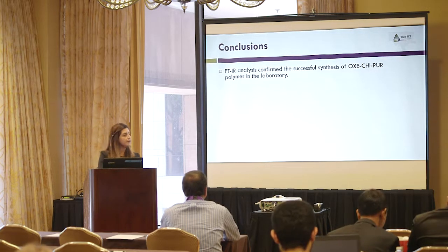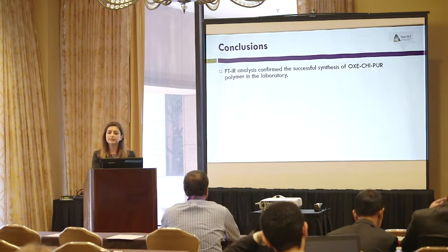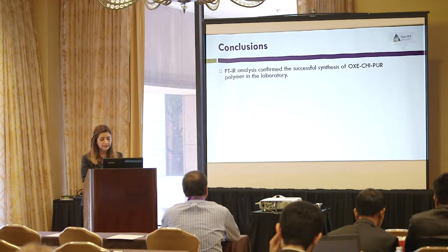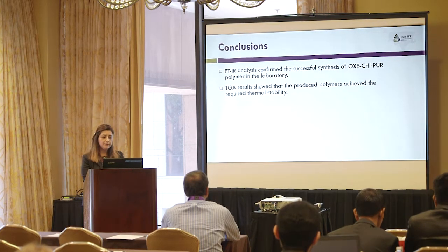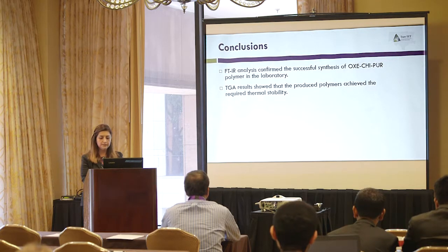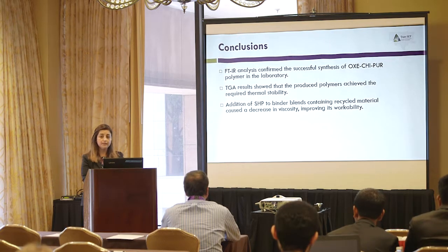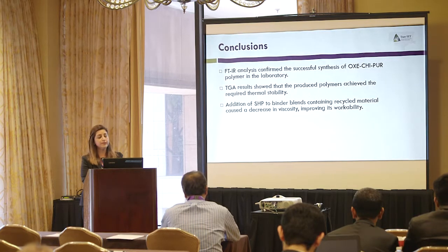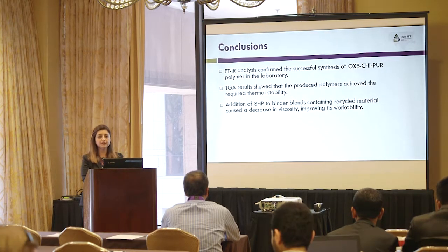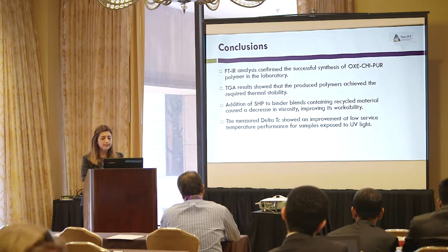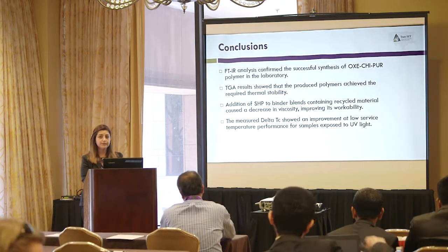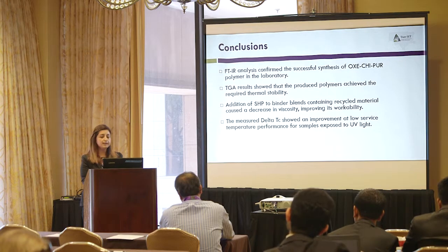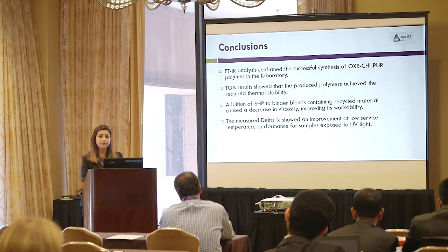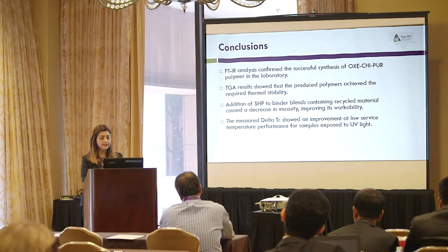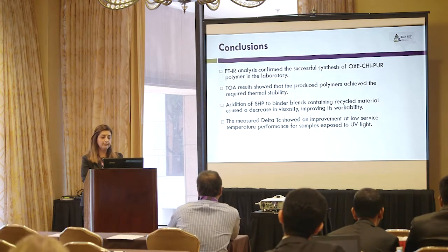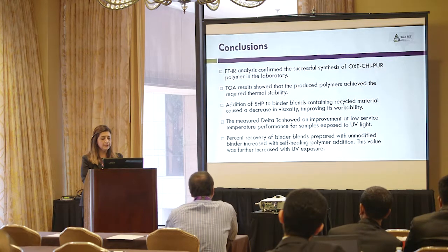As a conclusion, I can say that we were able to successfully confirm production of self-healing polymer material in our laboratory, and then we were able to gain required thermal stability for our self-healing polymer. Addition of self-healing polymer to binder blends containing recycled material was able to decrease viscosity and improve workability of the samples. Delta TC results from binder blends showed improvement in low temperature performance of the prepared binder blends by addition of self-healing polymer and then by exposing samples to UV light.